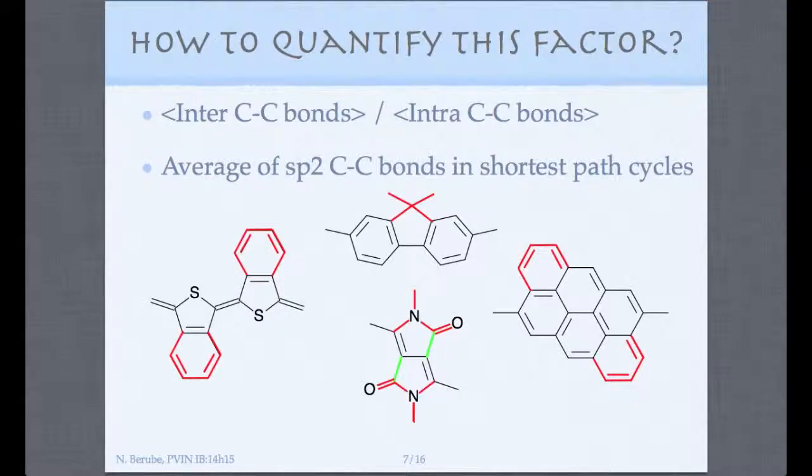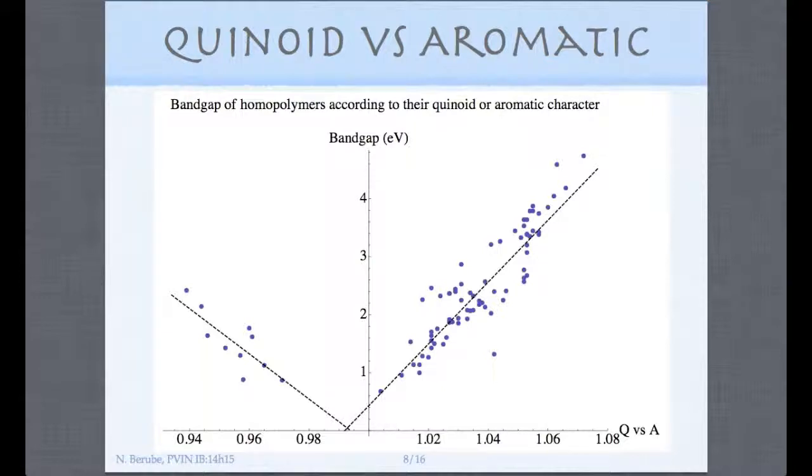And the parameter is only a secondary parameter in the model that we're going to use, in order to try to explain the relationship and guide the design. So here's the result. We launched this calculation on 87 homopolymers, and we find the same thing that Jean-Luc Brédas found 25 years ago, so yay, 25 years late. But the main difference from Brédas's study is that there we only had polythiophene in forced geometrical configuration, while here we have 87 radically different polymers from radically different families, all in relaxed geometrical structure, and they all tend to follow the same trend, in which low band gap lies in between the aromatic and quinoid.